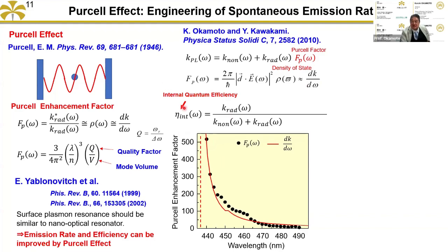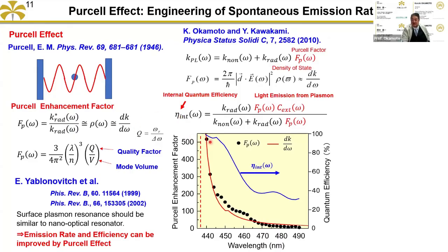Then the internal quantum efficiency of the light emission is the ratio of the radiative and non-radiative recombination rates. The Purcell effect should increase the radiative recombination, and then finally increase the internal quantum efficiency. That enhances the efficiency. And the good thing is that for this region, this dotted line is the best coupling region. In the best coupling region, the efficiency is almost 100%. So that's very important.